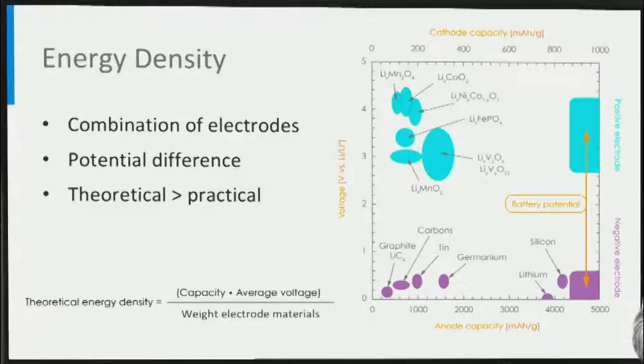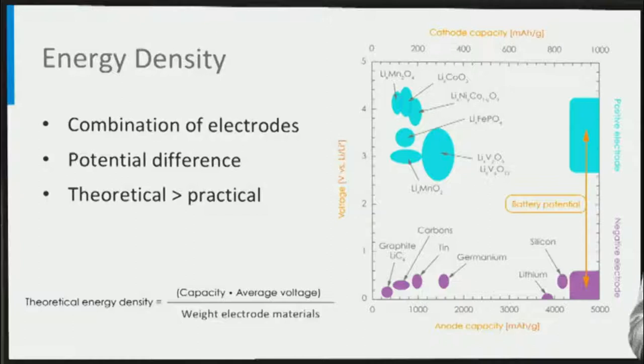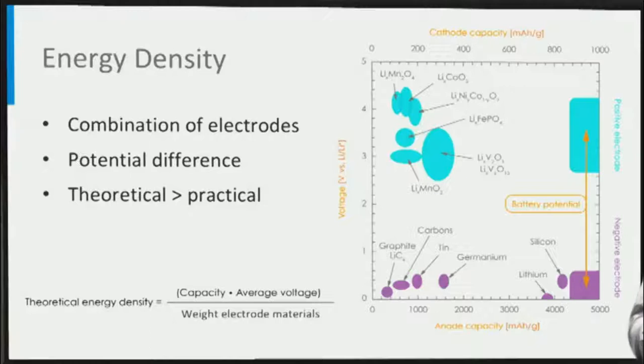Remember that energy density is the capacity times the average voltage. Therefore, the theoretical energy density of a combination of the two electrodes equals the capacity times the average voltage, divided by the total mass of the two electrode materials. The practical energy density of entire batteries is much smaller, roughly around 30% of the theoretical energy density, because of the weight of the non-active materials including the electrolyte, current collectors, and packaging. Both the specific capacities and average potentials of existing electrode materials are known, making it possible to calculate the energy density of any combination of electrodes. The potential of electrode materials is typically referenced to that of lithium metal, which is conveniently set to zero as reference potential. This has no consequence because the battery voltage is always a difference between electrode potentials.